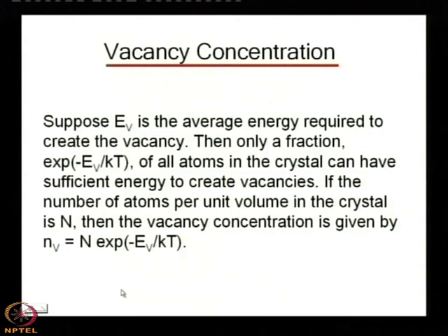Actually, if E V is the average energy required to create a vacancy, then only a fraction given by exponential minus E V by k T of all atoms in the crystal can have sufficient energy to create vacancies. And if the number of atoms per unit volume in the crystal is capital N, then the vacancy concentration is given by capital N exponential minus E V by k T.